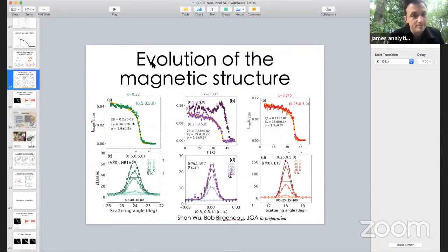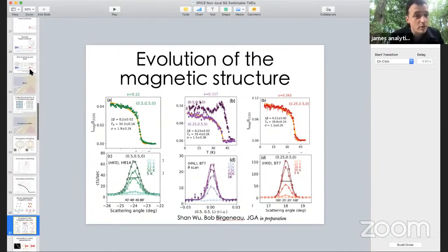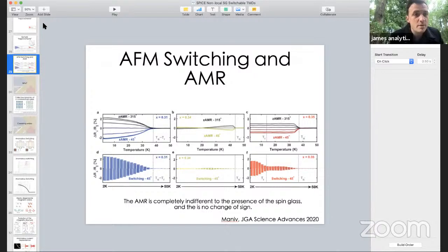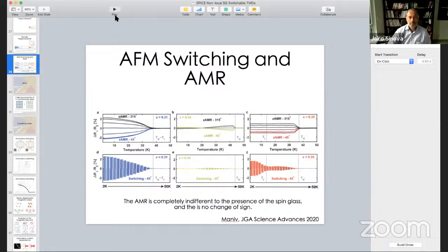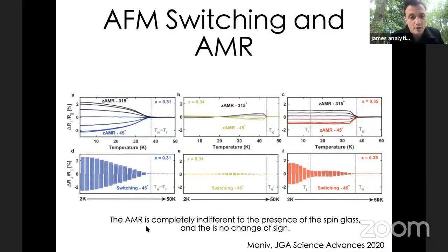What that seems to have done is open up another channel of spin transport. And as far as we know, that's the only way we can understand this very unusual temperature dependence of this over-intercalated sample, where you start to see the sharp growth of the efficacy of the switching without there being another magnetic transition of any sort. The only thing that's happening at this lower temperature, where you start to see a growth in the switching, is that the spin glass freezes. The collective dynamics of the spin glass turns on. So even though we don't understand it, it seems to do something cool.